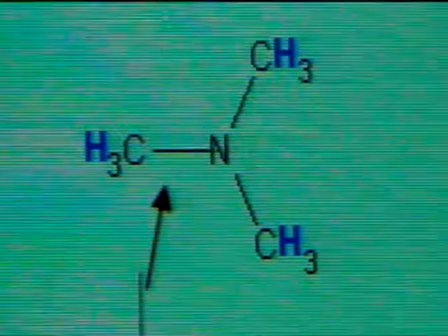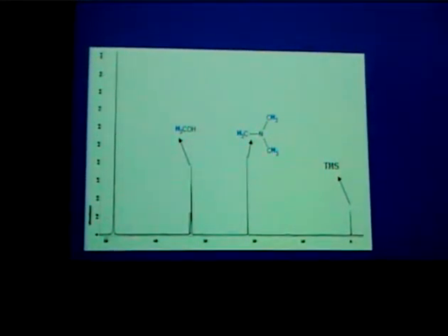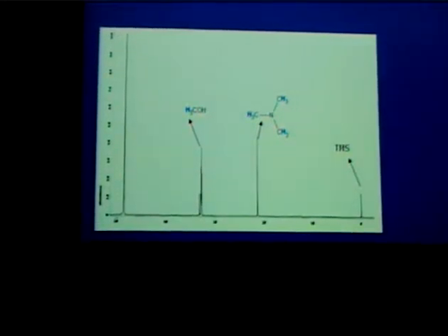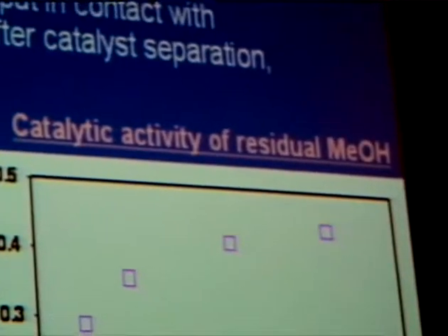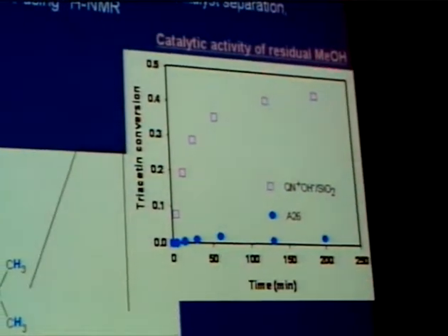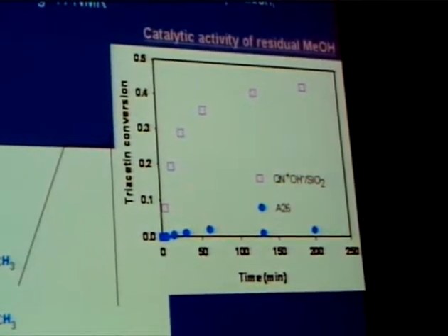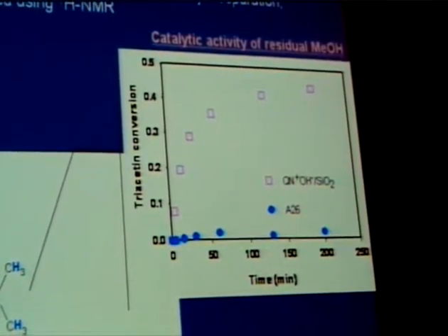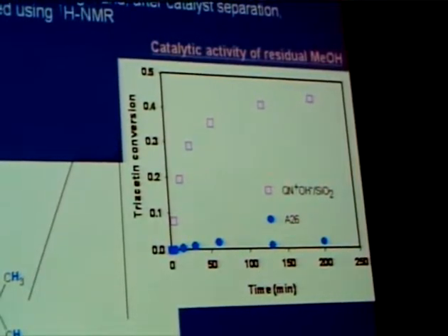And that would explain why the catalyst is being deactivated, because since you separate the liquid phase after every cycle, you're taking some of the sites out. When you use, for instance, the alcohol from this leaching experiment by itself in a reaction with triacetin, you see that there is activity for that alcohol, confirming that you have species that are active for transesterification. So yeah, there was leaching.